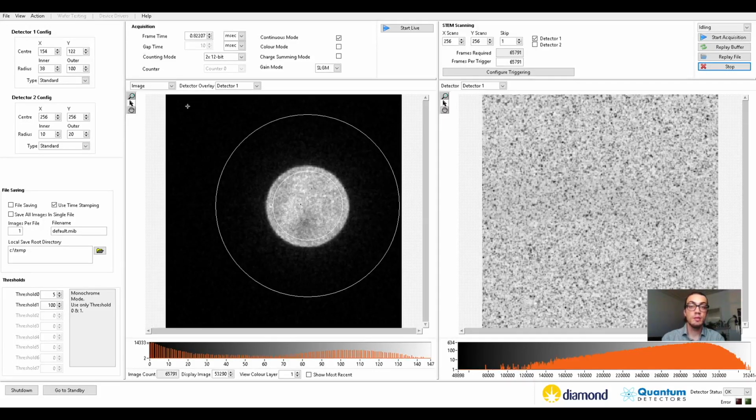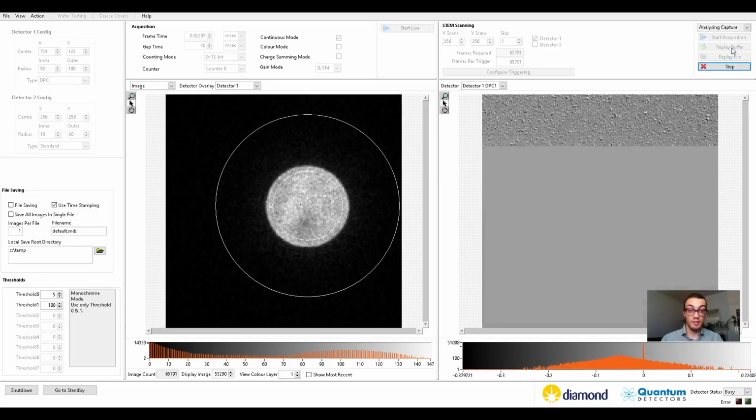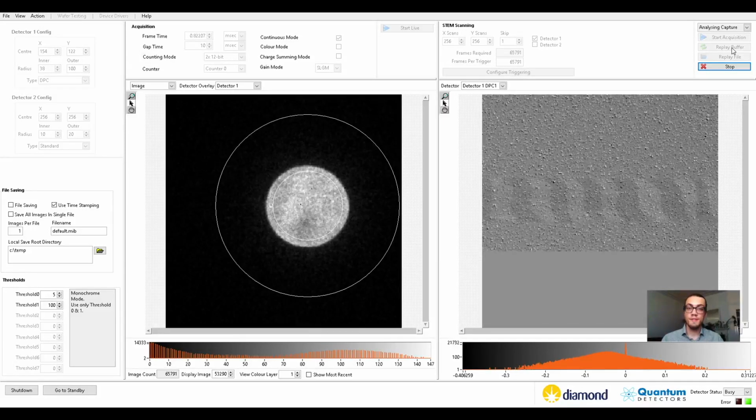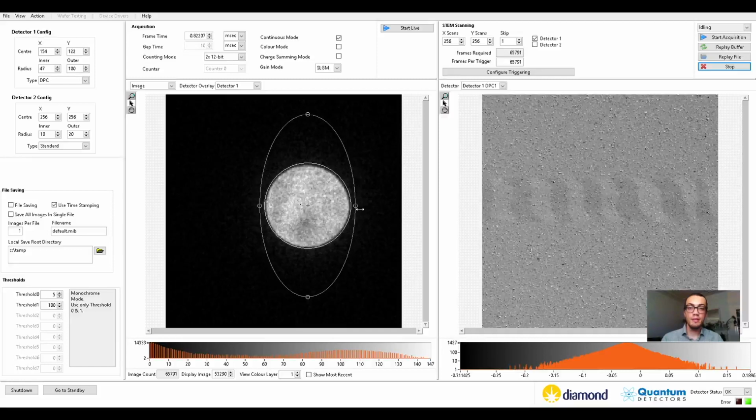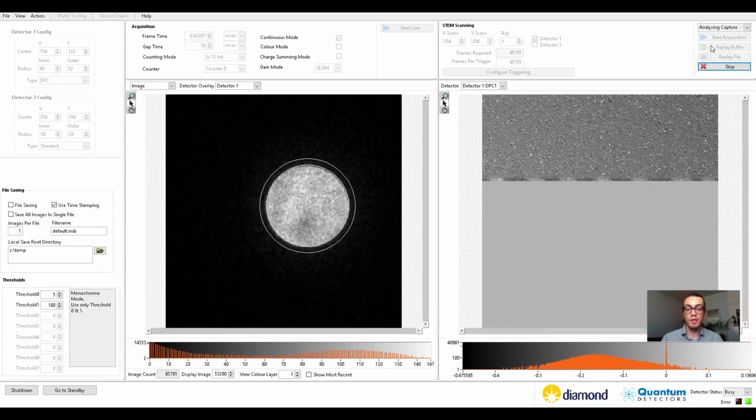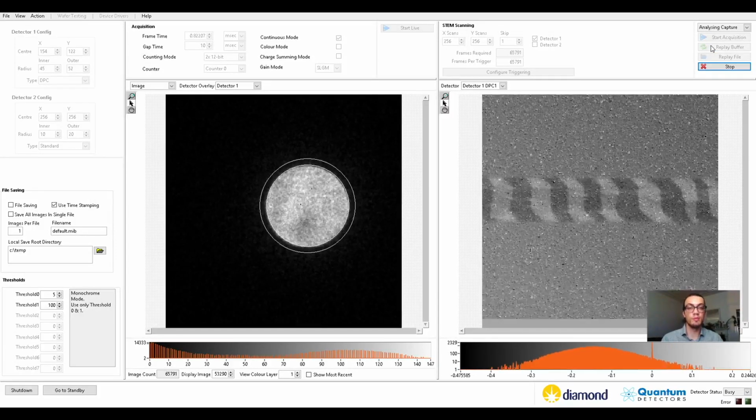In this case, the annular detector overlaps with the bright field disk, and we mostly see grain contrast from the crystalline sample. We will now come back to DPC detector and show an example of different annular detector size. Firstly, we include a lot of signal from the bright field area, and the magnetic induction result is therefore rather noisy. By making the internal radius just overlapping with the outer edge of the central beam, we can maximize the DPC signal to noise. There are also other, more advanced methods to generate even better contrast, but they are computationally expensive and harder to implement for live imaging.